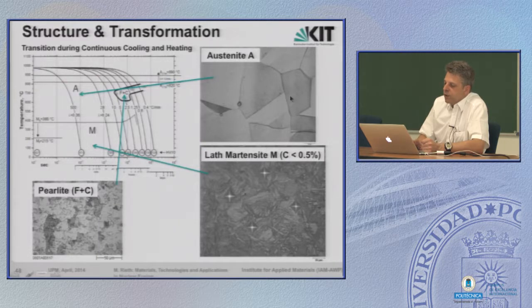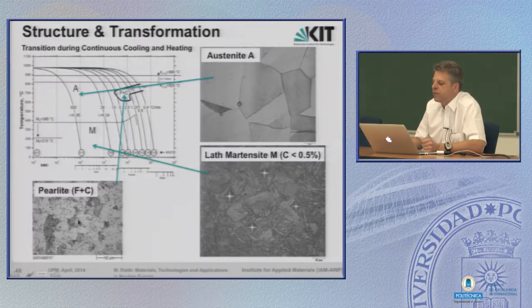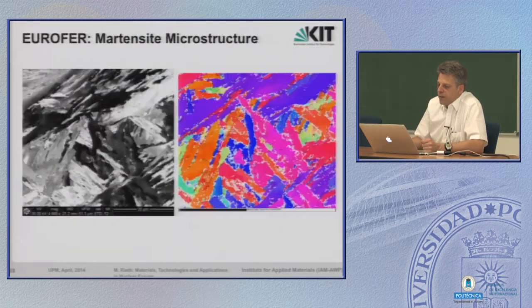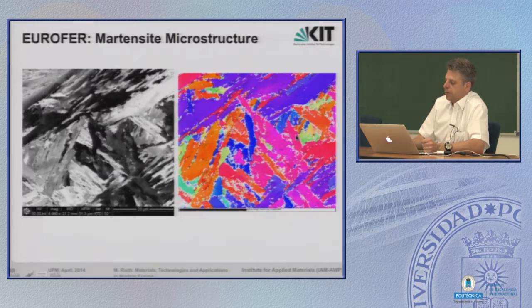Also, the phases we have already seen. You have to bring it up into the austenitic phase, then it looks like that. You can quench it down, then you have a typical lath martensite structure. But you can also cool it down quite slowly, within 1 or 2 days from 1000 degrees to room temperature, and then it looks quite different. Then it forms pearlite and ferrite, and then it is a quite soft material. So all these things you can do with Eurofer, but you cannot do this with austenitic steels. This is again another EBSD image where you can see this very fine martensitic lath, which contributes to the hardening, to the strengthening of this type of steel.